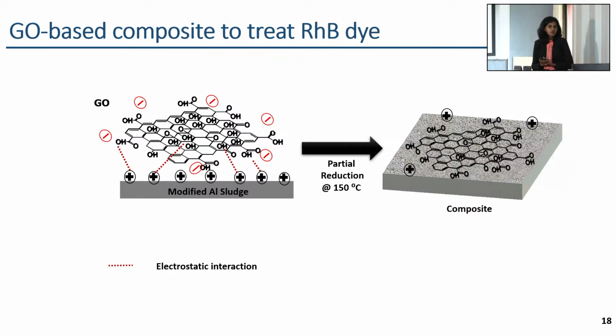Here, these modified aluminum sludge particles are positively charged. The charge was measured using zeta potential values. Due to the presence of oxygen functionalities, graphene oxide is negatively charged. So, during the mixing of graphene oxide with modified aluminum sludge, the graphene oxide is coated on the sludge particles through electrostatic interactions. Then during the partial reduction at 150 Celsius, some of the basal plane functionalities are removed, restoring the graphitic basal plane. Therefore, at the end of the process, we obtain the GO-based composite with partially reduced graphene oxide.